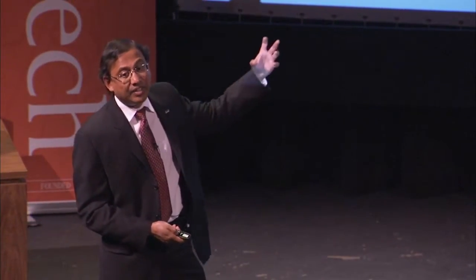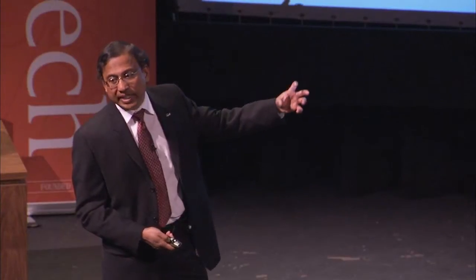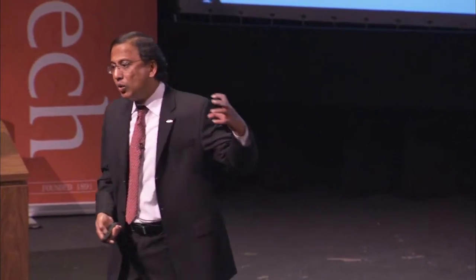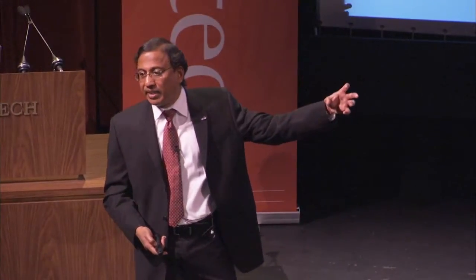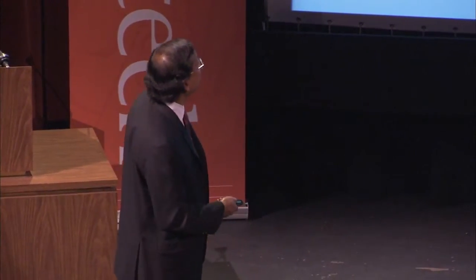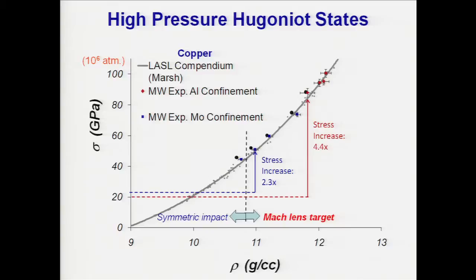We can get an equivalent velocity of 4 kilometers per second. I'm making my gun look like it is shooting projectiles at 4 or 5 kilometers per second rather than at 2 kilometers per second. And that's what is shown here. So we can achieve, if I had a symmetric impact and homogeneous targets, then this is the range of pressures I could explore.